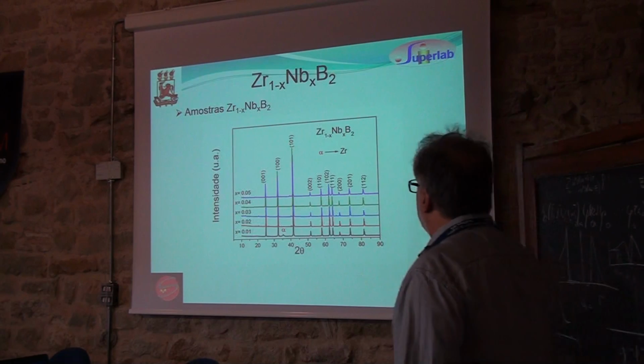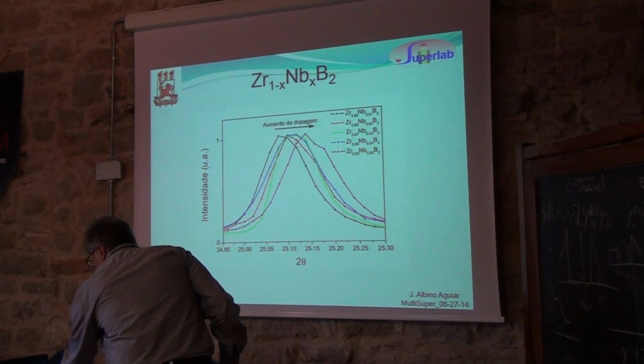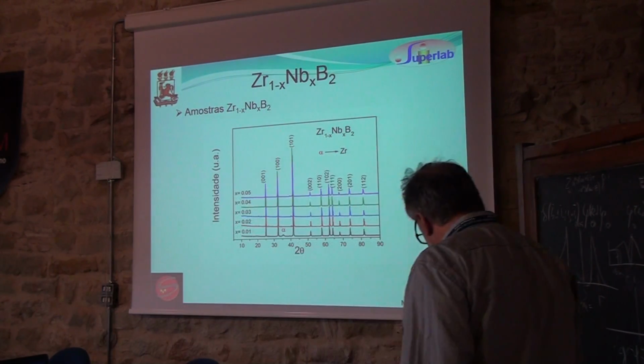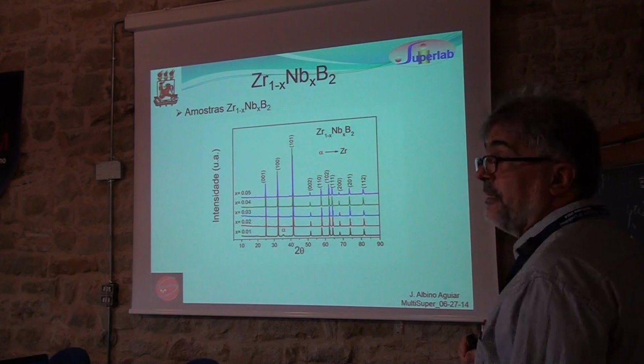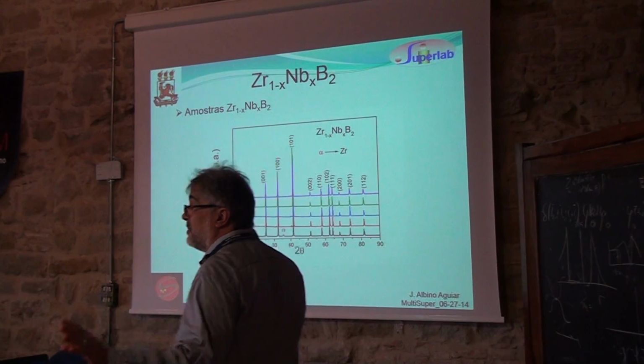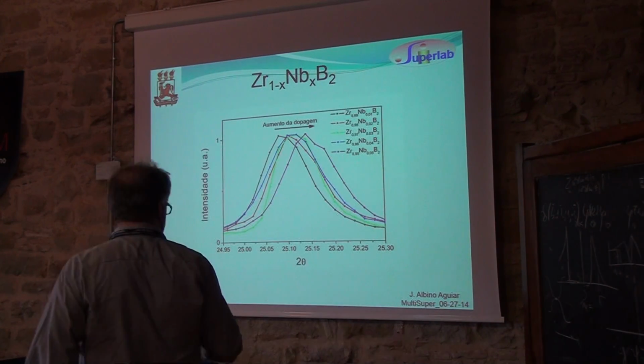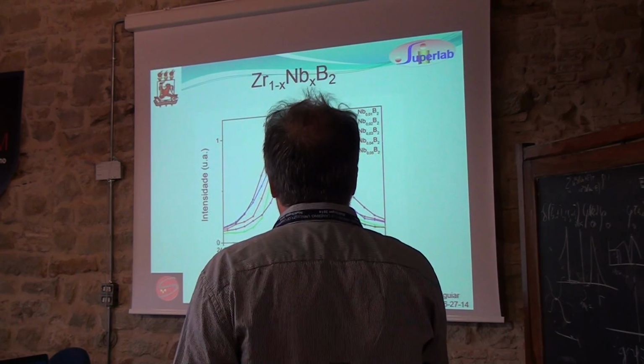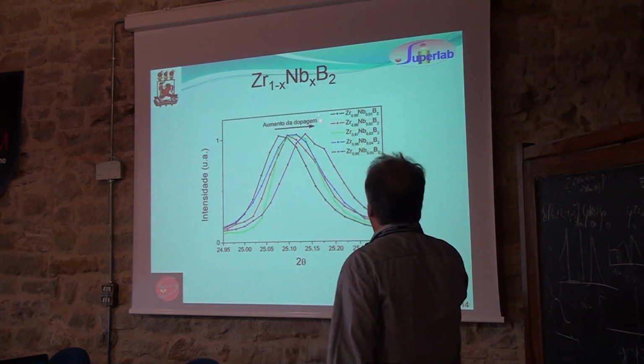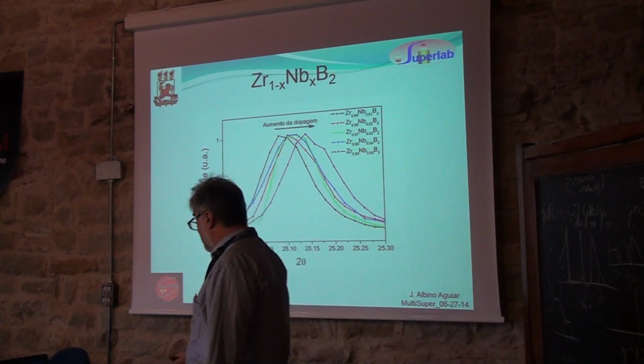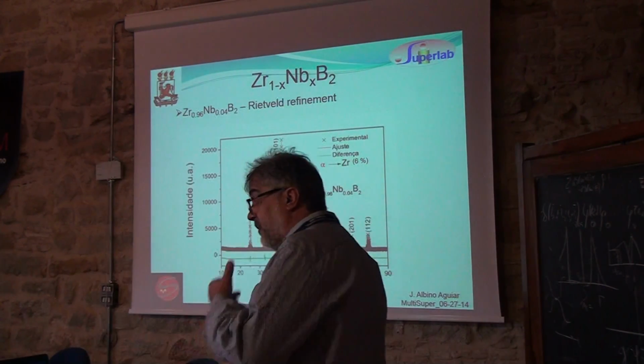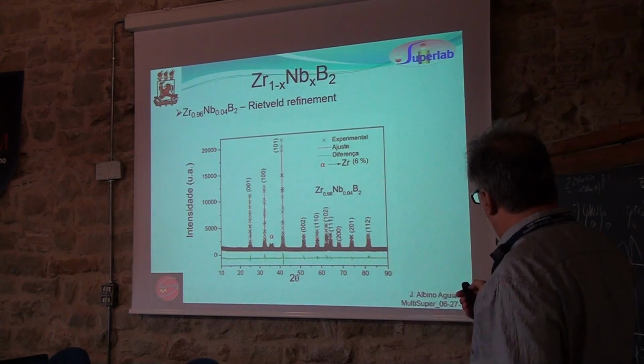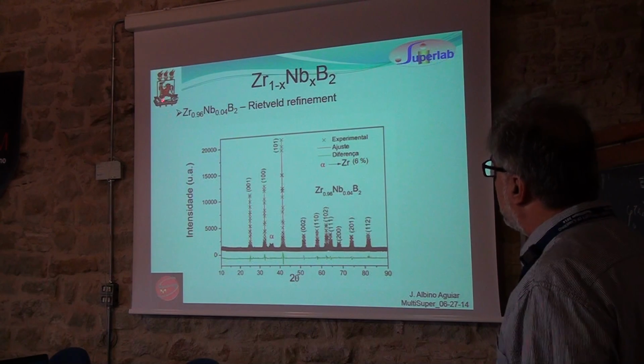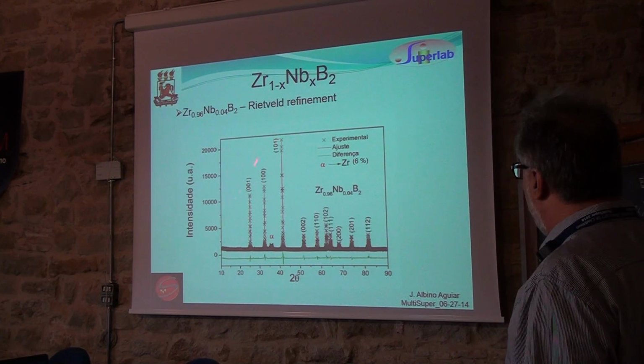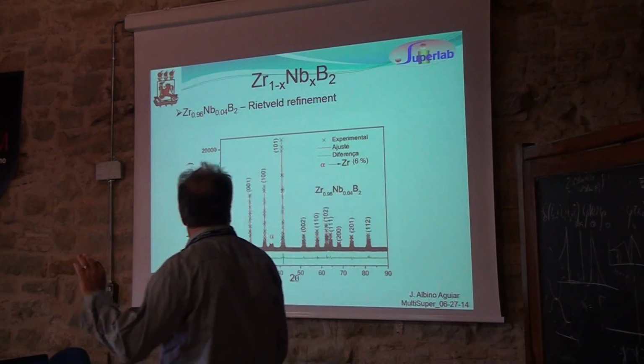And here you see the X-ray diffractogram for this material. And you see that we have some zirconium impurity here. But zirconium is not a superconductor, so there's no problem for us. You can make the rocking curve, and then you see that, sorry, it's in Portuguese, but you can understand this: intensity, and this is increasing dopant concentration. The peak moves to the right, so it's a proof that we are changing the lattice parameter. We do Rietveld refinement, for example, for this sample, and we can fit everything perfectly.